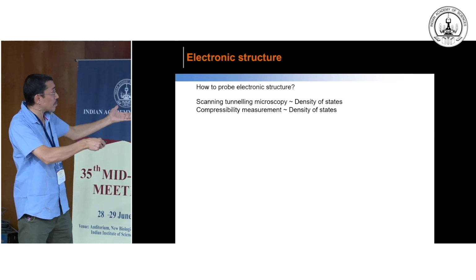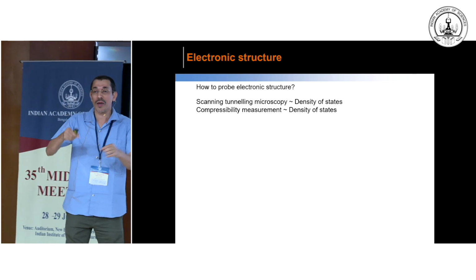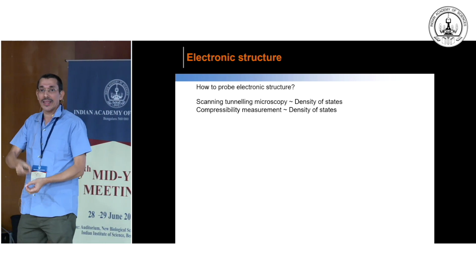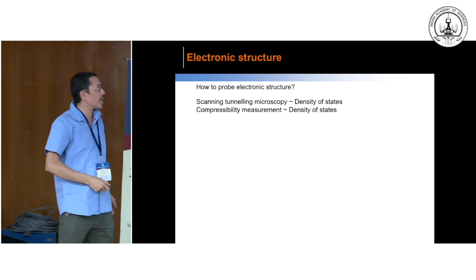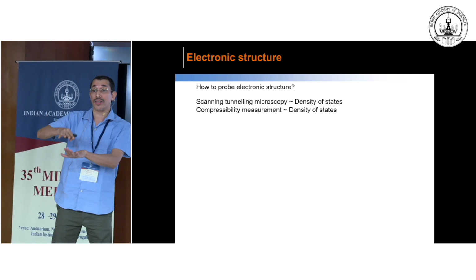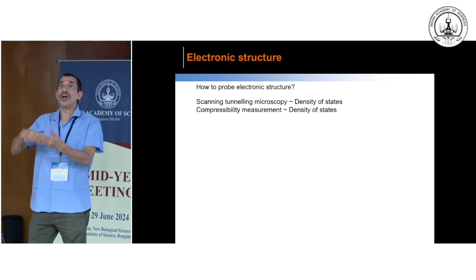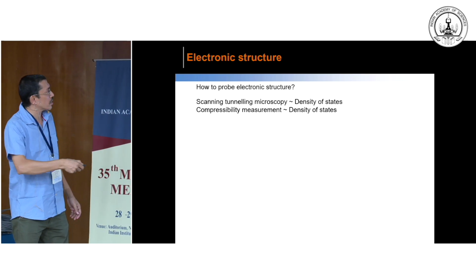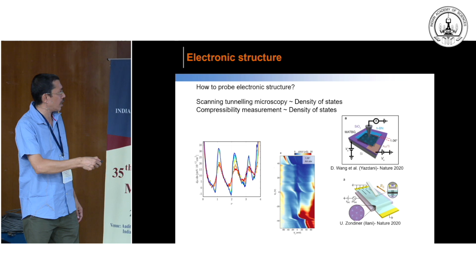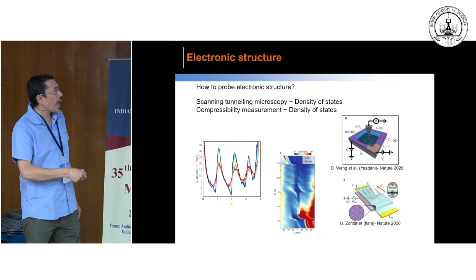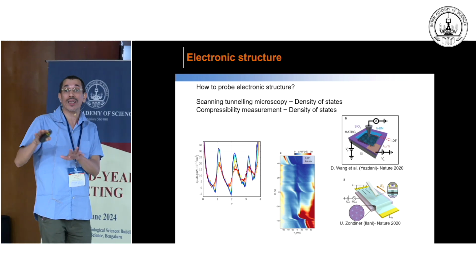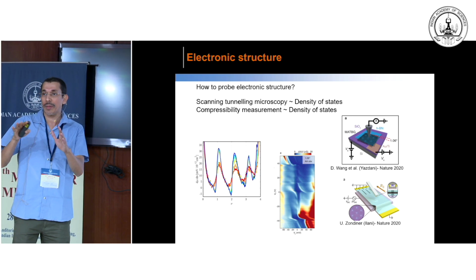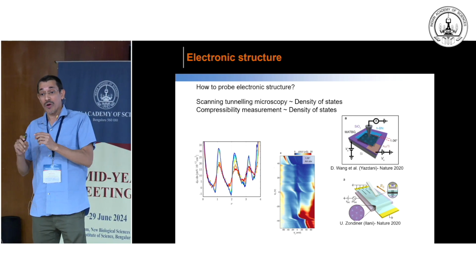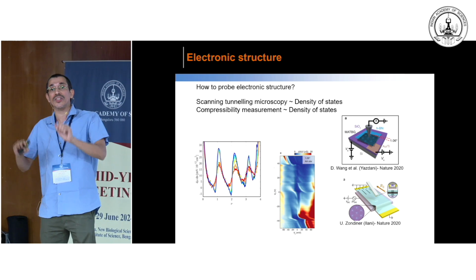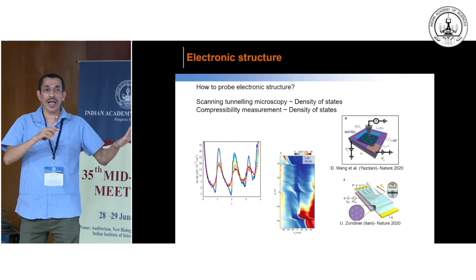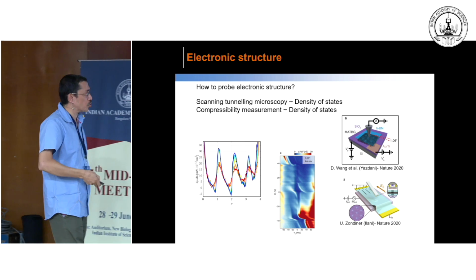What measurement techniques have people used? For example STM, because with STM you can measure tunneling density of state, and that way you can find your electronic structure. Or people have used capacitance measurement or compressibility measurement, which can give you the thermodynamic density of state in the system. So these are the probes, these measurements have been shown, and they also show some signature of that non-rigid band. It shows that the bands are actually not rigid. Once you fill carriers, the band actually keeps changing, the way I was talking about with that cartoon, the glass picture I was showing.